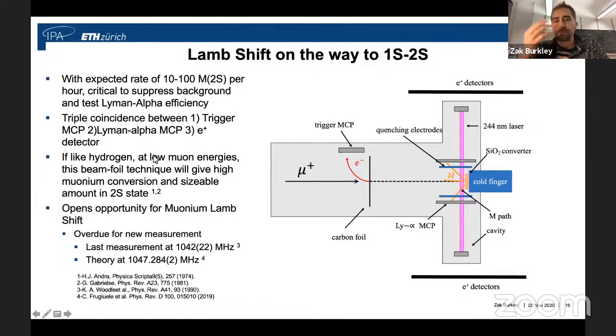However, we realized if, like hydrogen, then at low muon energies, this beam foil technique of sending a muon beam through a thin carbon foil, it could give high muonium conversion and actually a sizable amount in the metastable 2S state. And since we already have quenching electrodes and Lyman alpha detectors for measuring atoms in the 2S state, we could imagine, well, then we can actually do a muonium lamb shift measurement as well. And this is very overdue for a new measurement. The last measurement was 30 years ago with an uncertainty much, much larger than what theory is at.